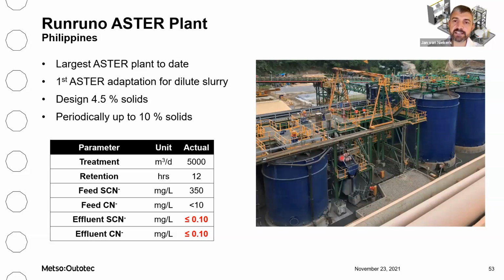The cyanide detox product is then diluted to the design of 4.5% solids, but periodically it goes up to 10% solids for the aster section. So the treatment rate for Randrano is quite high at 5,000 cubic meters per day, but again at relatively low thiocyanate concentrations due to the dilution, but again achieving very consistent results. This water is then pumped up to the tailing storage facility, and overflow water is returned to the process.